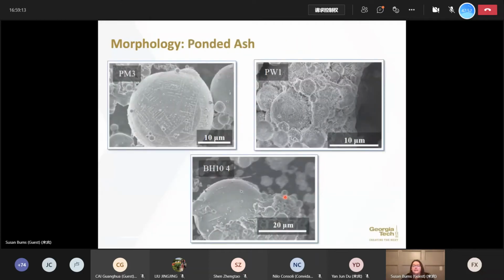Now let's look at an ash that's been sitting underwater in the southeastern United States, meaning it's pretty hot and humid throughout most of the year. And what you'll see is a different morphology than what we've seen in some of the previous SEM images. You can see here that we've got a change in the surface texture. So we've got residual weathering effects which have come in and dissolved some of the elemental or molecular mineral phases that were here, and they've redeposited them on these particle surfaces. You can see some cementation effects here as well, and just essentially change or evolution in the morphology of these ashes.